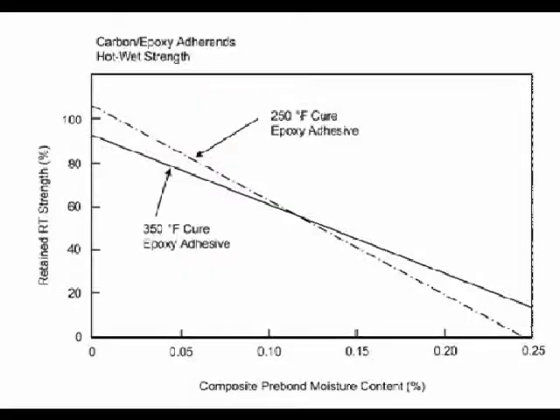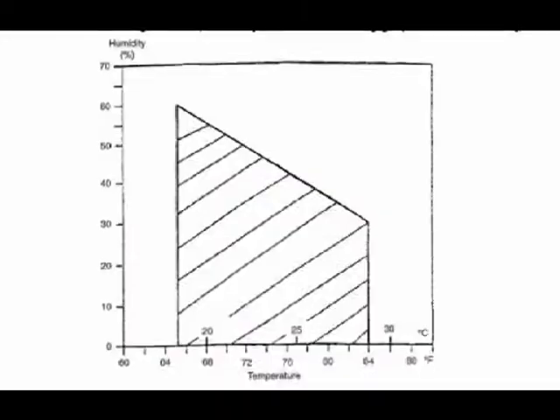and practice. Very small amounts of moisture at the pre-bond stage of manufacture can cause dramatic reductions in part strength after the curing process. One study shows that the room temperature strength of a 350-degree epoxy resin part with absorbed moisture is only 20% of that part without the presence of moisture. And this was created by allowing moisture to be absorbed at a rate of only 1/4%. So what are some practical approaches to eliminating water damage during the preparation of composites for curing?